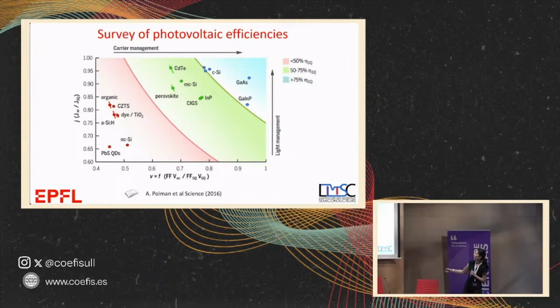So you have materials that are bad and materials that are very good. You see gallium arsenide is very good. You see crystalline silicon is very good at collecting a lot of current and less good at the voltage. And if you want to collect power, power is current times voltage. So you want high voltage and high current in your photovoltaic device. You also have other materials like gallium indium phosphide. This is what is in the satellites and others here.